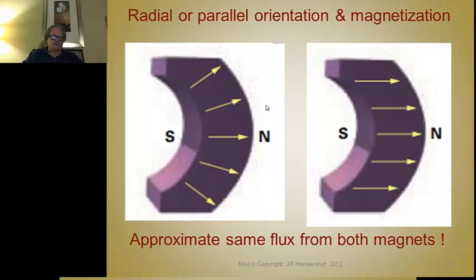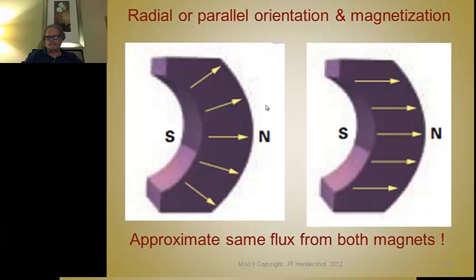When you manufacture the magnet — no matter how it's made — you can orient the powdered magnet material. In the case of ceramic magnets, it's like a wet clay with particles of strontium ferrite colloidally suspended in water. Before firing, you can subject all these magnets to a magnetic field to orient all the tiny magnets, which significantly affects how strong the magnet is. You can orient them radially, as shown on the left, or in parallel, as shown on the right.